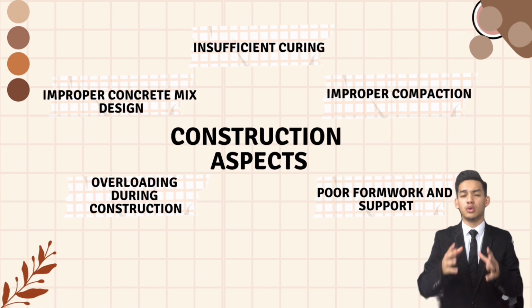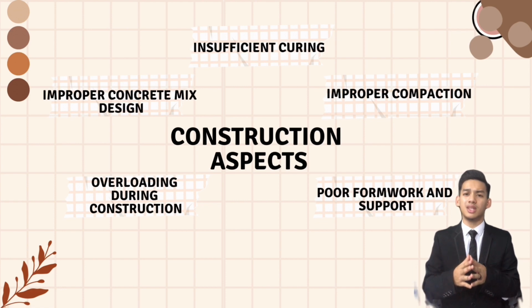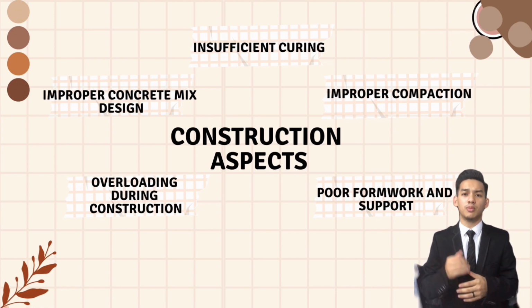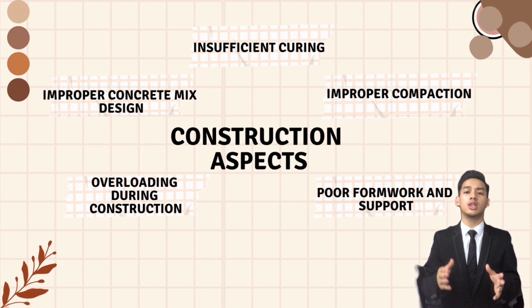Construction aspect must follow conformity to the standard of work practice and specification. The first point on the construction aspect is improper concrete mix design. Shrinkage and cracking or less resilience to environmental pressures might result from a poorly formulated mix. Next is insufficient curing. A weak slab prone to cracking can be produced by insufficient or incorrect curing practice, such as inadequate moisture retention or early removal of foam or curing materials.